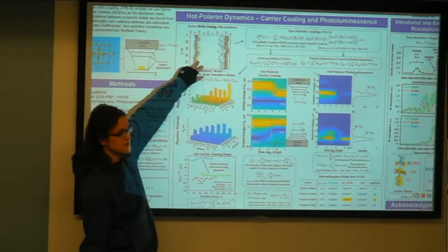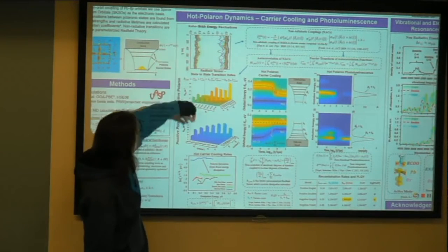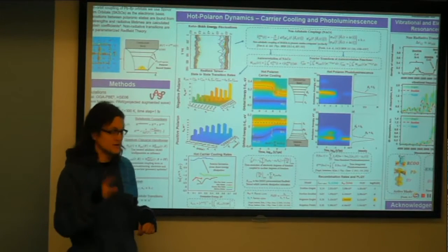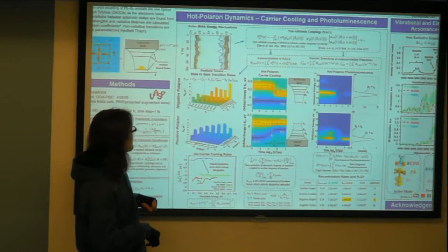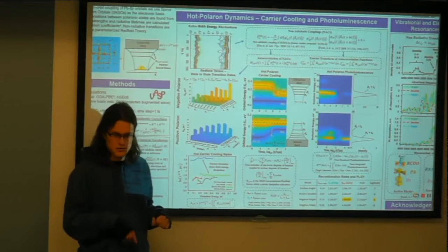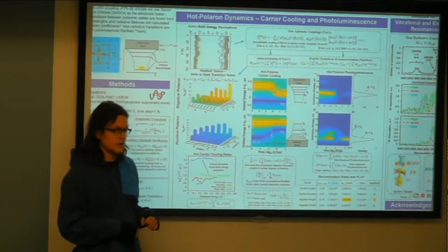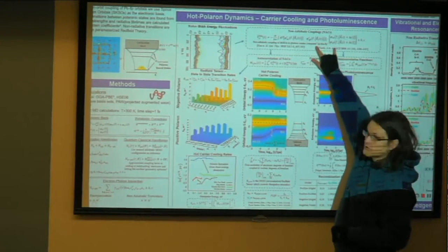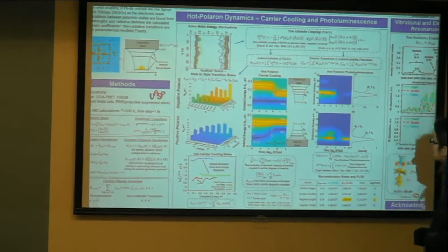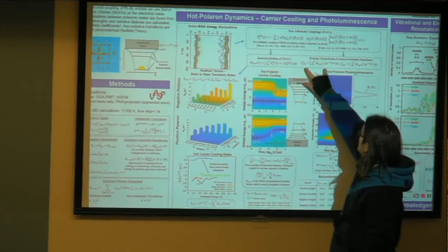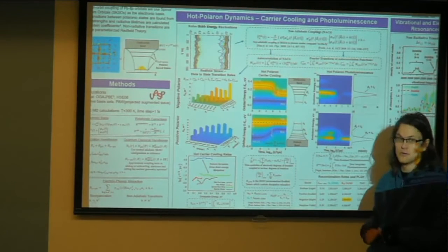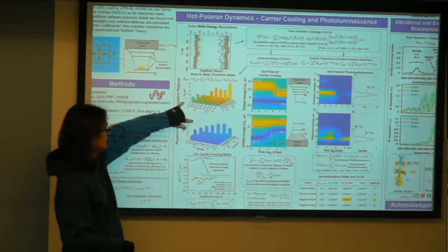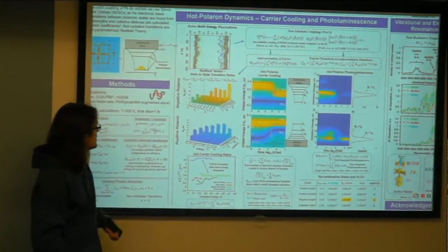So that's visualized with this figure, which is upside down. But essentially, due to static electron-phonon interactions, you get fluctuations of the bands. And then those frequencies are for the normal modes that the electronic states couple to. If you extract those, we compute non-adiabatic couplings in our spinor basis along the trajectory, and then just doing correlation functions and Fourier transforms, we can convert those into rates of transitions between each of those states, and those are visualized here, which we call our Redfield tensors.